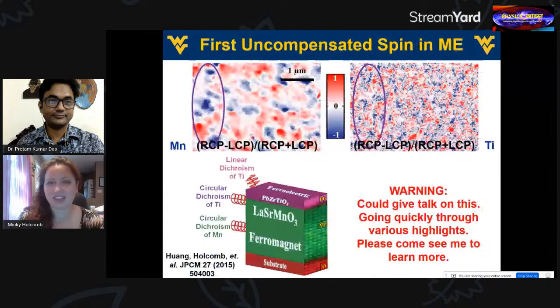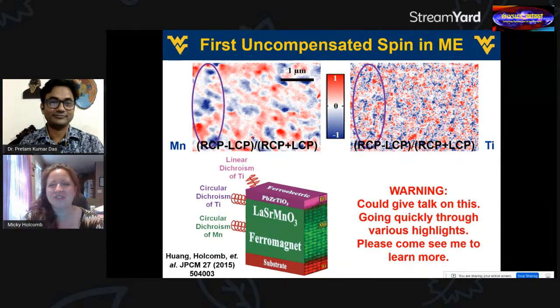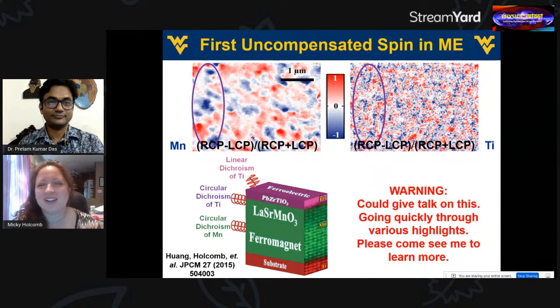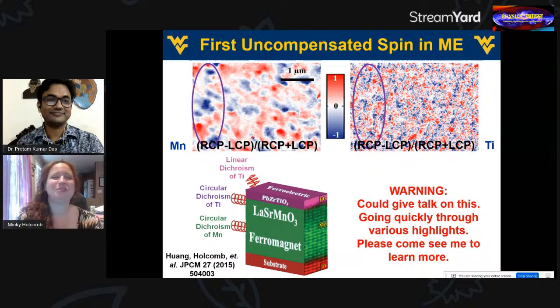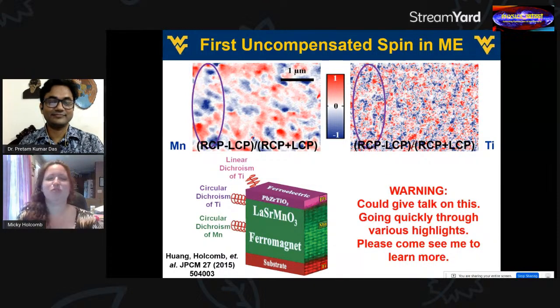Now, I'm going to admit that it wasn't quite as simple as the other example that I've shown you, the pretty example. Oh, look at how these domains are so beautifully coupled across these systems. It's not quite as beautiful, at least in this system. So on the left here, I show you the magnetic domains, which are very similar to what you saw in the cobalt example. On the right, I'm showing you the uncompensated spin at the interface. And an untrained eye would be perfectly valid in claiming, I am not certain there is any correlation between these two images. And I wouldn't blame you for that at all.